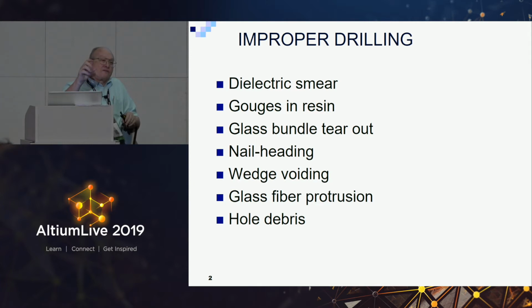So these vias are very, very tiny, and we use a laser. Well, that's an enormously more complicated technology than mechanical drilling that we've been doing for 200 years. And there are a lot of places you can fall into, and this is only partial: dielectric smear, gouges in the resin, glass bundle tear out, nail heading, wedge voiding, glass fiber protrusions, hole debris.